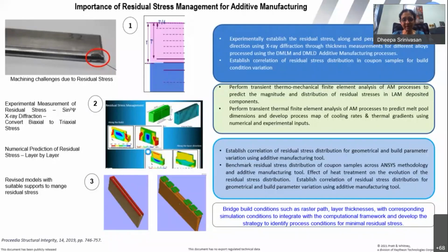So in this particular geometry, if I have to measure residual stresses before I weld it to my cast FSX 414, or develop these DFAM struts that we designed to be able to remove it without distortion, for example, residual stresses are really very dangerous, because in a very thin additively manufactured section such as this blade, they can actually change the dimensions, and so on and so forth.